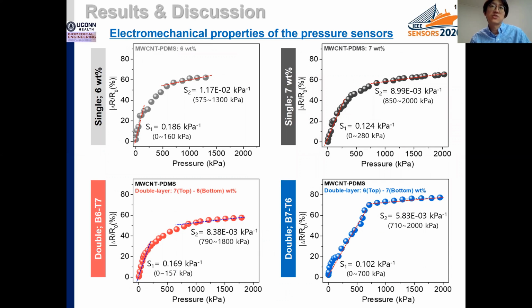This slide shows the relative change in resistance of composite sensors under different pressures. As you can see from the data, all the sensors exhibit two distinct regions with different sensitivity. In the case of single layer sensors, when the MWCNT concentration increased from 6 to 7%, the linear response and the pressure range limitation were improved up to around 280 kilopascals and 2 megapascals respectively. The enhanced results are attributed to the decrease of distance between neighboring MWCNTs due to the high filler composition ratio in the PDMS matrix.